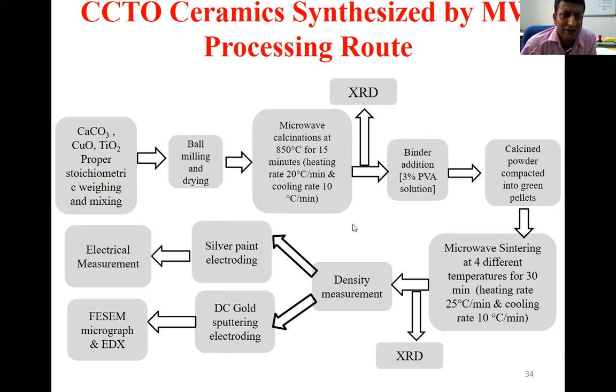Again for this system, we optimized the calcination temperature at 850 degrees Celsius for 15 minutes, whereas in the journals, when we do conventional heating, the optimized temperature is about 1100 degrees Celsius.